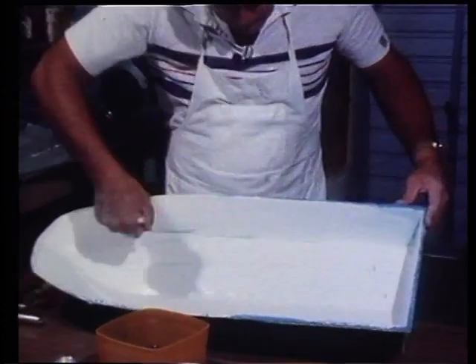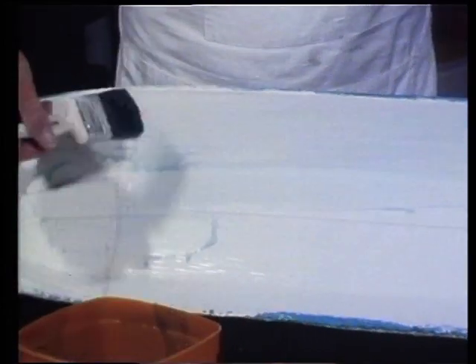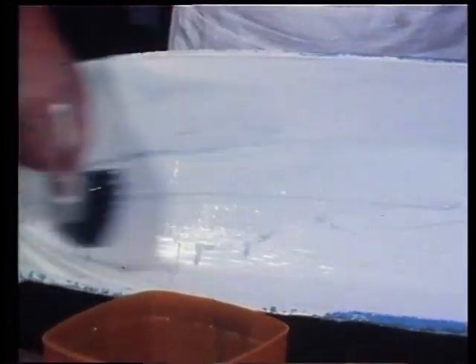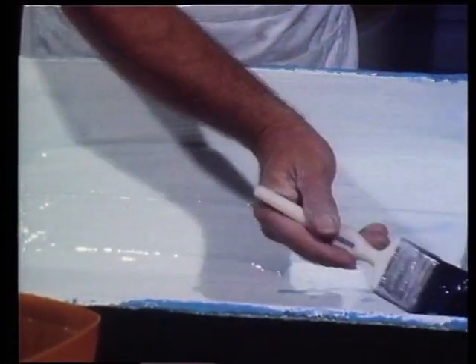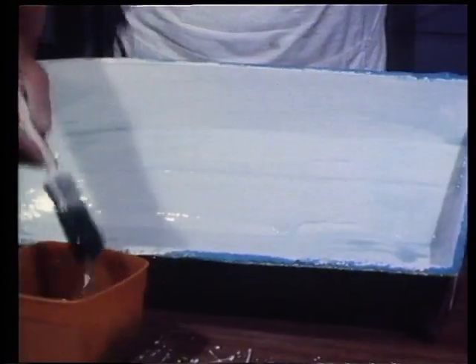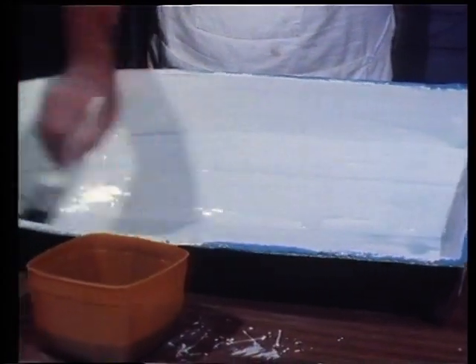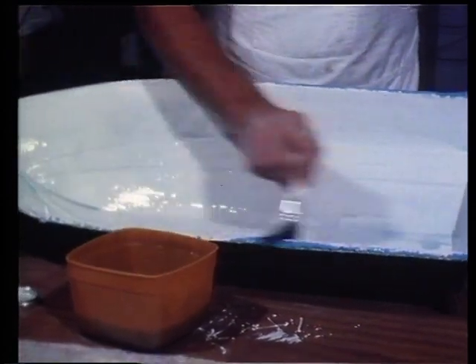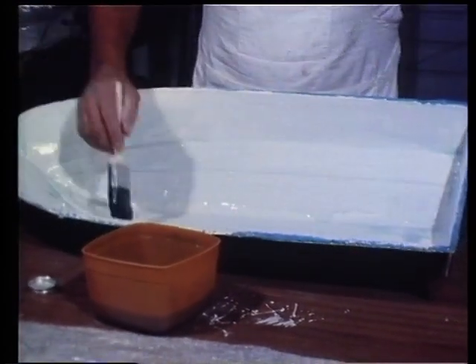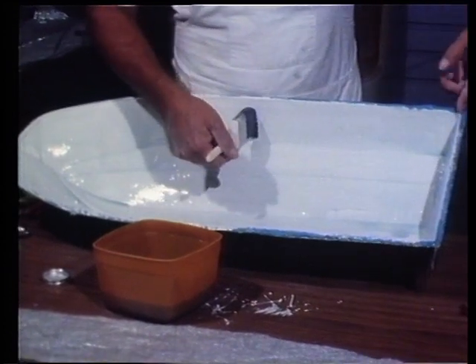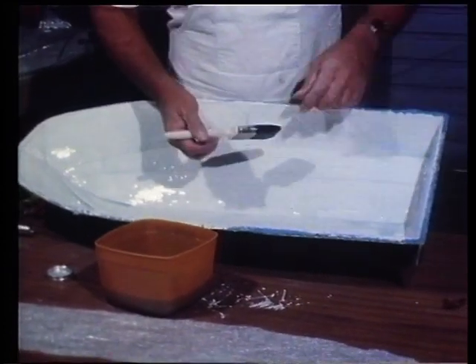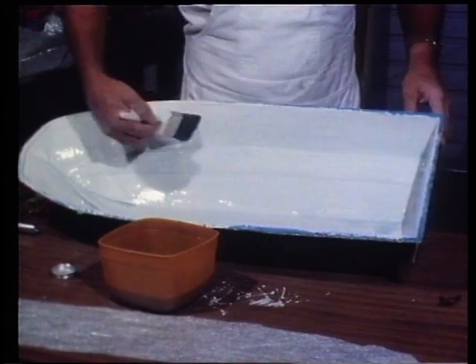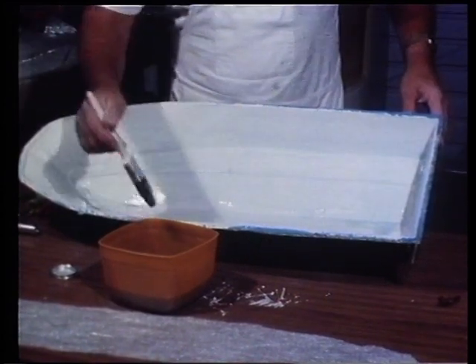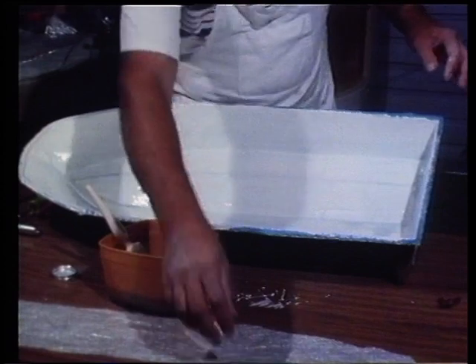Firstly, you lay quite a substantial amount of resin, a generous amount of resin, into the mould. You really get that resin and brush it into the mould so that it's covering 100% of the surface. Now, obviously, in this model boat mould, I can look at laying up virtually the entire hull in one go, but with a larger boat, you would break it up into sections. You might say take that length from the transom along the top side and look at that as being the section that you were laying up with one particular batch of resin and one particular amount of glass.